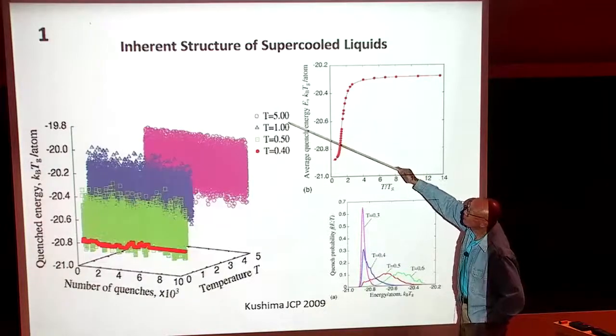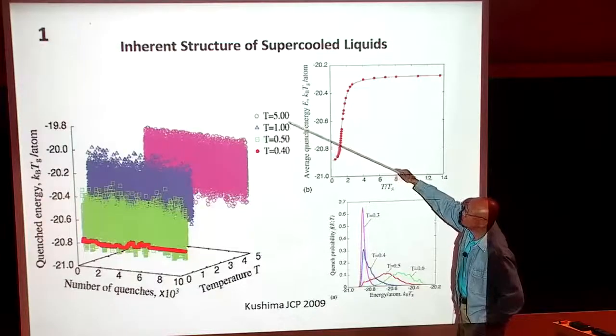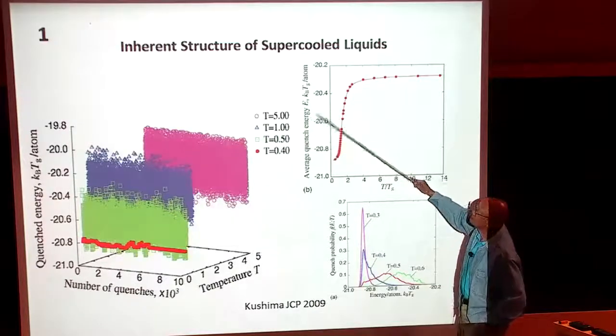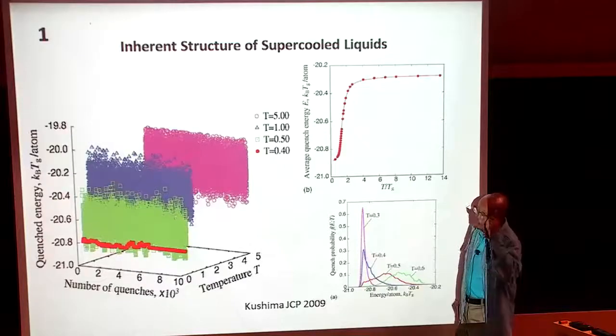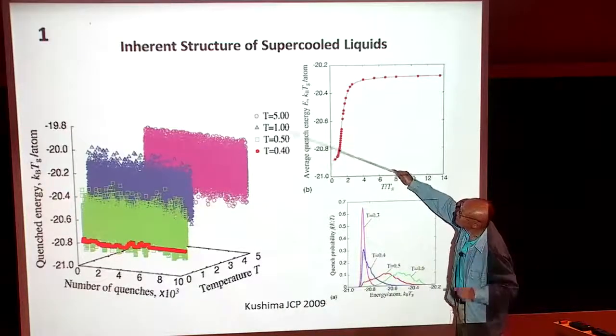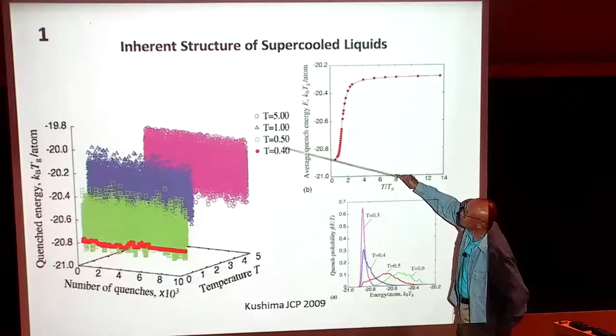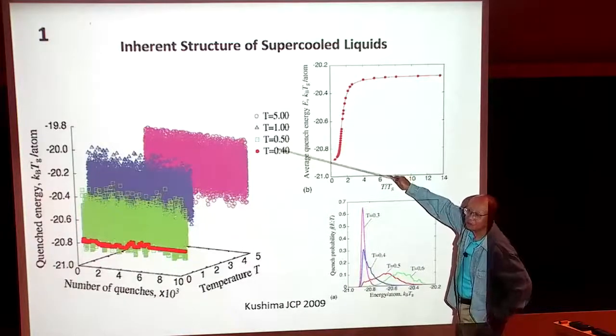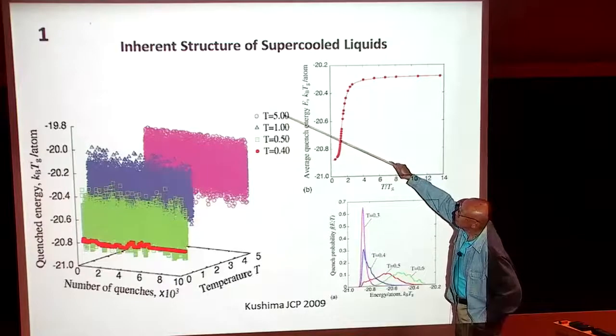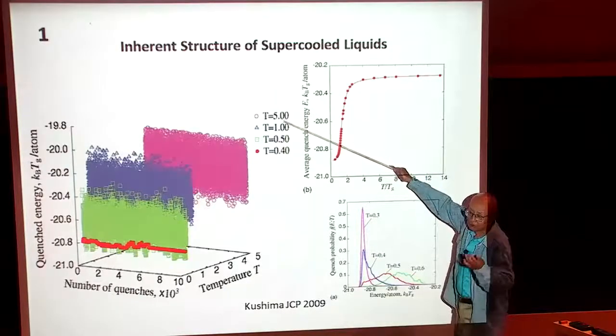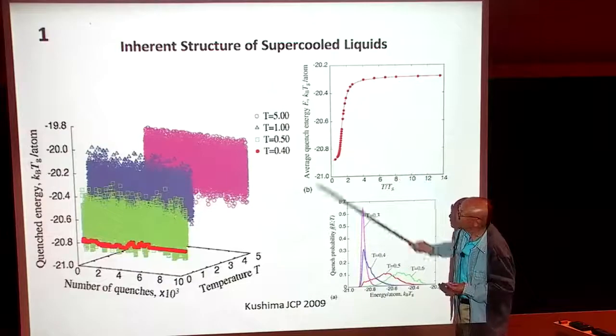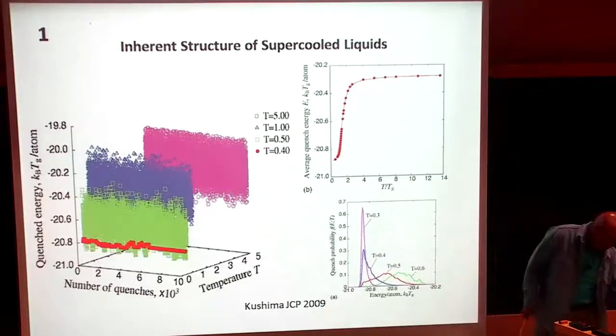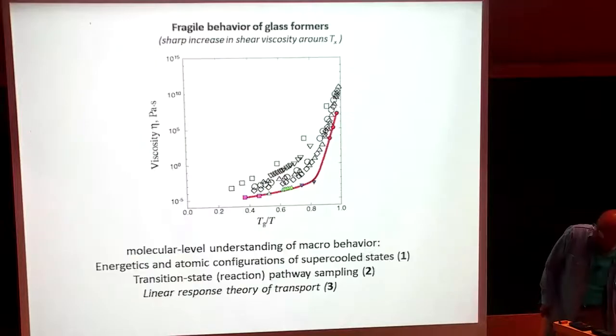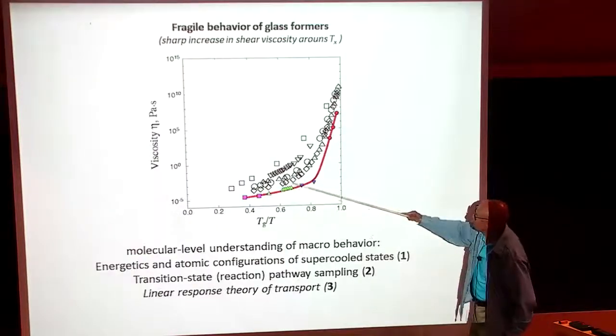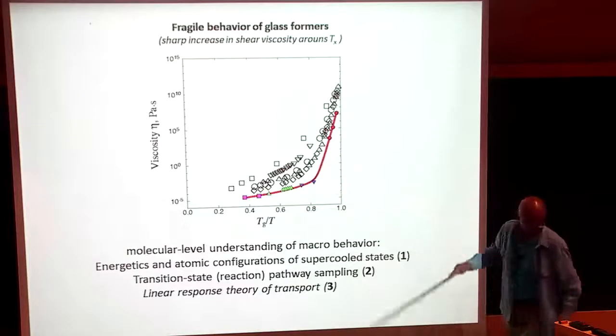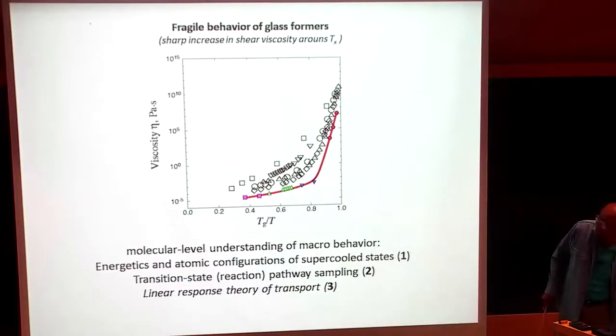So in this case, this T is in some appropriate unit. The glass transition temperature, Tg, really means around 0.37, somewhere down here. That means you can operate at high temperature, not quench, you just simply operate at high temperature. Then you are really in the high temperature, very low viscosity regime. So you're really here. If you want to think about what's going on down there, you have to go down to a temperature about 0.37.